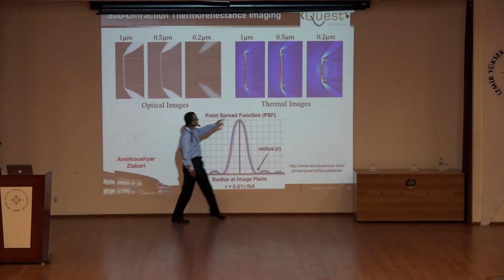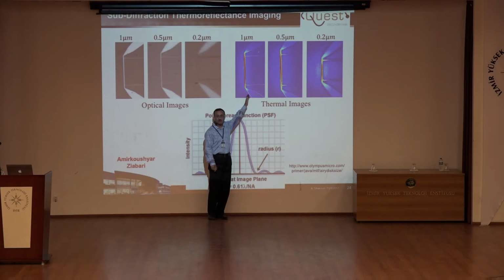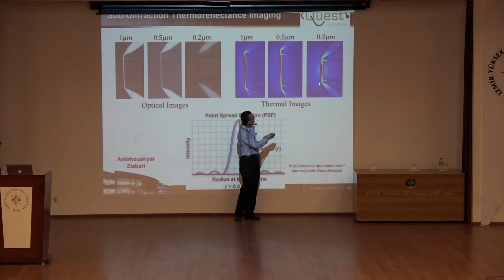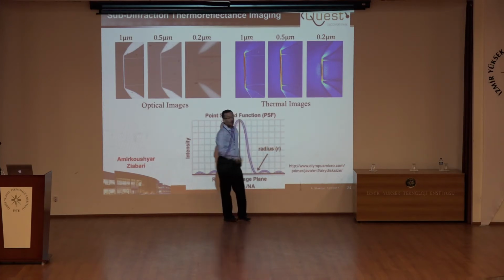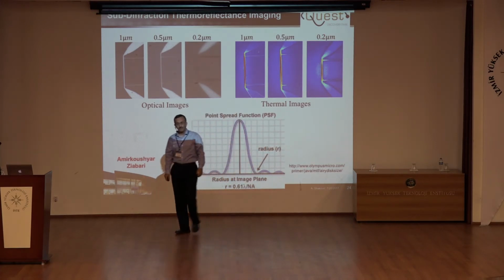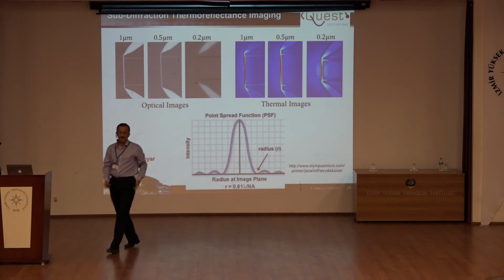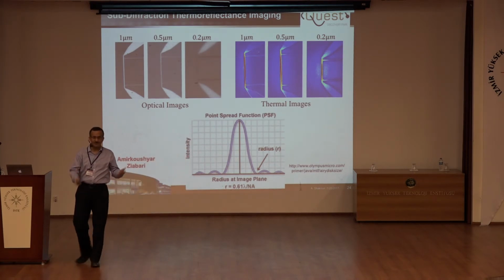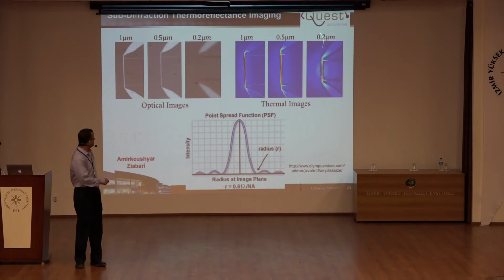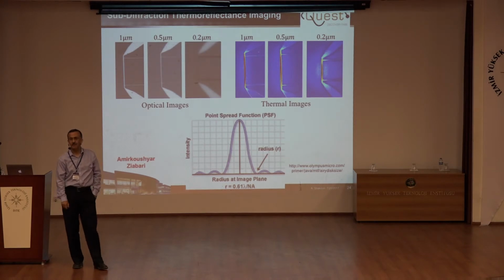What we were surprised by is that, of course, at 1 micron, you measure the temperature, you see how the current goes, how it heats up here, beautiful heating. But we can even measure the temperature out to 0.2 micron. You know, as an experimentalist, well, this is what we measure. So it looks like we are breaking the laws of diffraction to measure temperature, but it applies to optics. Any ideas how you can break the laws of diffraction?